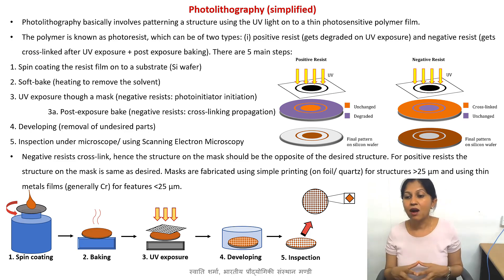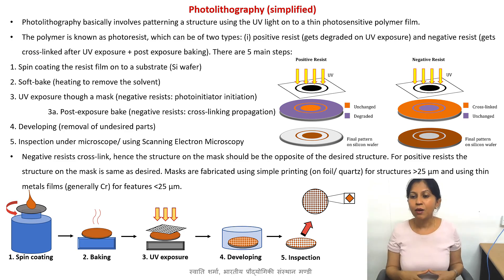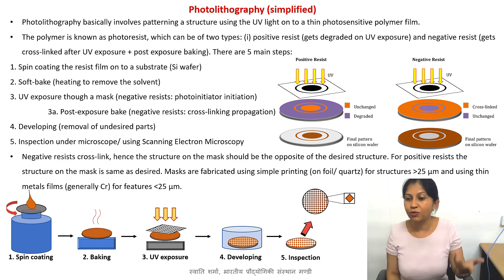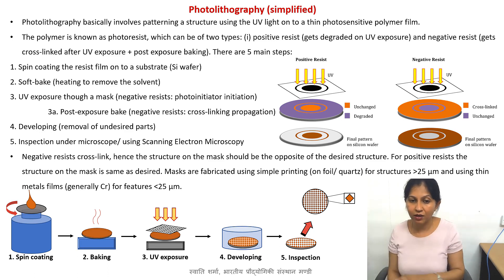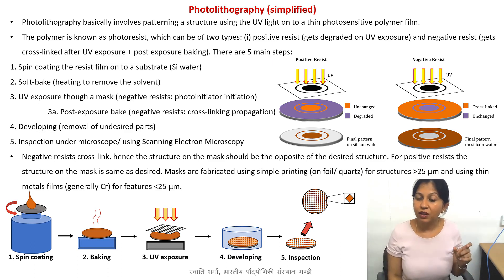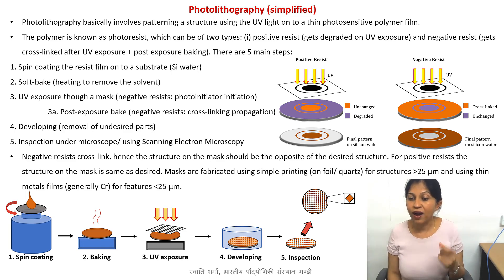These masks are either fabricated onto foil, like transparencies, where you do printing with specialized inks. This printing method only works for structure sizes up to 25 micrometers. For structures smaller than 25 micrometers, you will typically require more expensive masks prepared using electron beam lithography, using chromium as the metal. That can give you very fine feature sizes down to 5 micrometers, and even smaller than 5 micrometers has been reported.